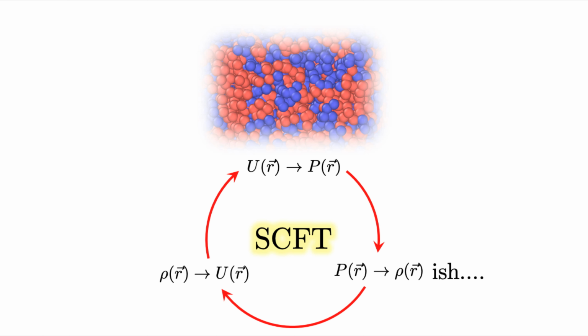Self-consistent field theory works well when polymers are long, and is rigorously accurate when polymers are infinitely long, but it still does a pretty good job when polymers are quite long, especially when the distributions are sharply peaked enough that there won't be that much deviation, like deep into the ordered phases. This is why the tops of the phase diagrams that I showed earlier look so similar between theory and experiment.